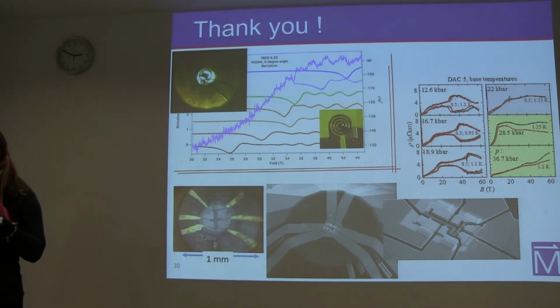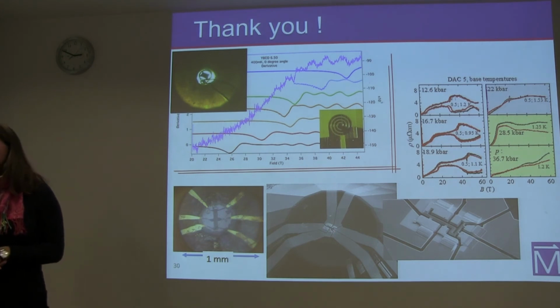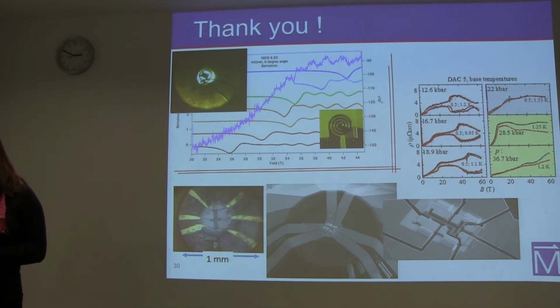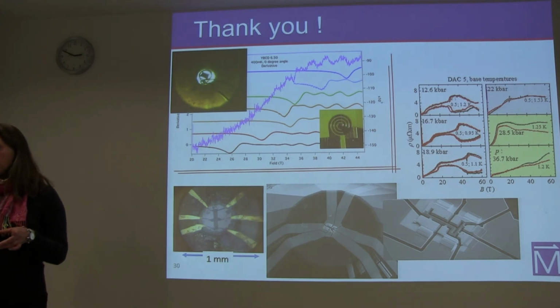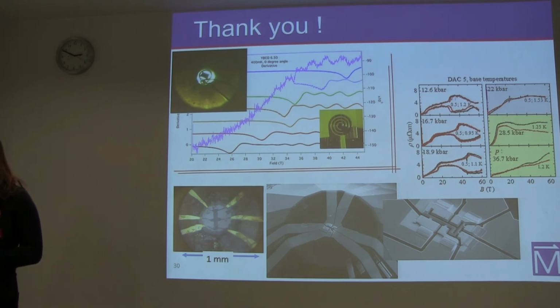You mentioned just briefly at the end that somebody was applying pressure along the a-axis. Have they done it along just the c-axis to see the effects? So they have done the three axes, A, B, and C. They have published only the results on the a-axis, but at one of the conferences, I think the March meeting, Le Taillefer said that by applying pressure along the b-axis, he does not recreate the charge order. So it's really the a-axis, not the b-axis. And along the c-axis, nothing much happens.